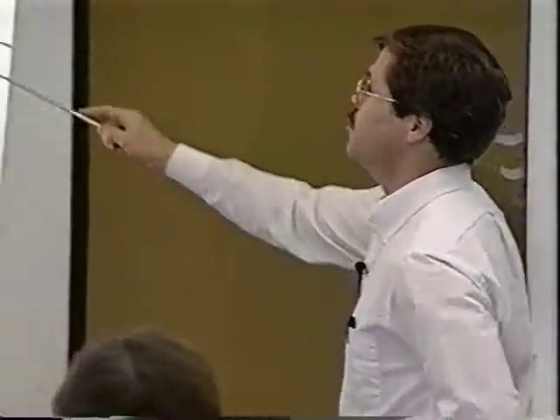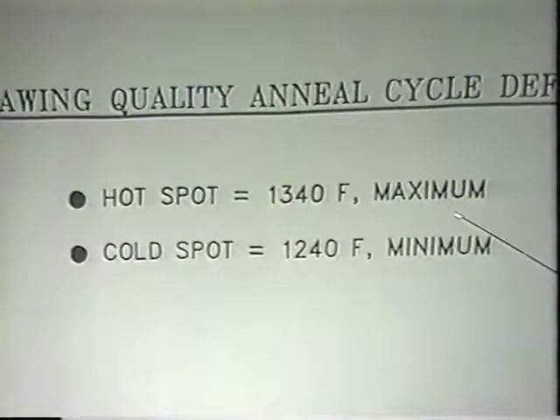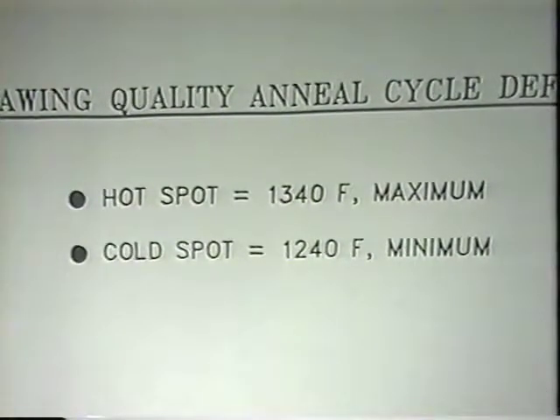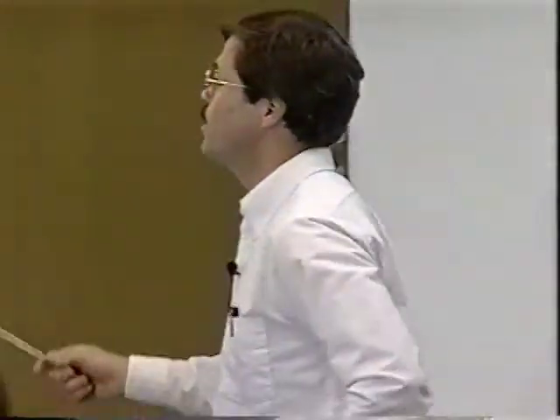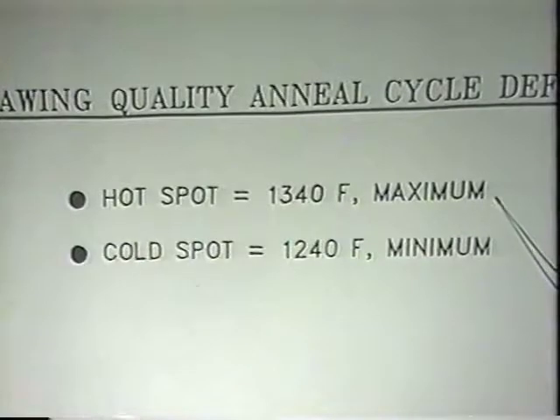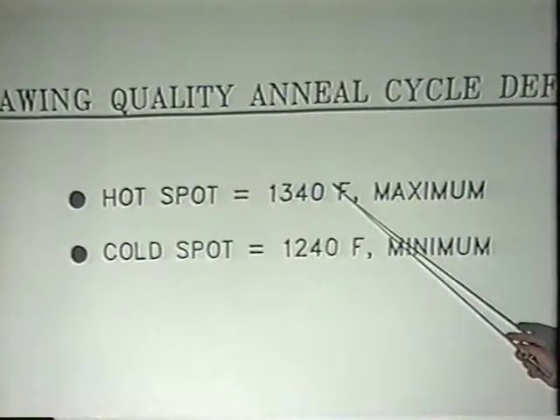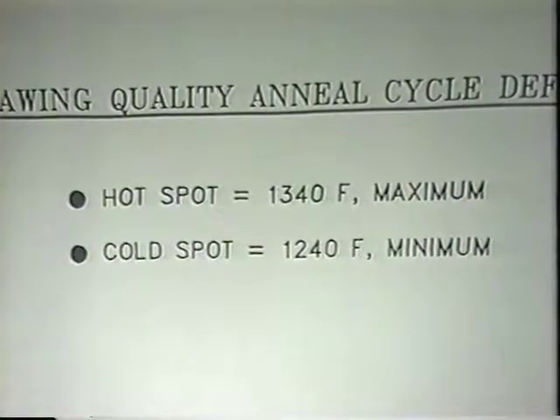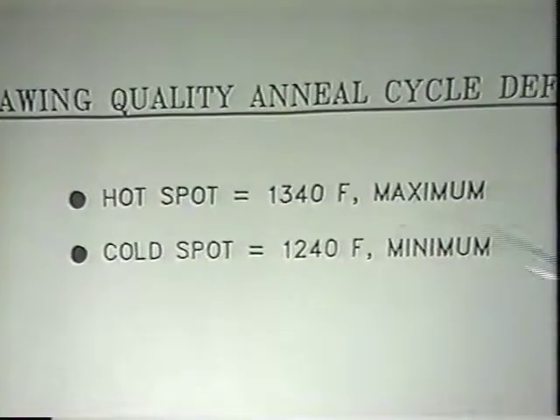We can make this window smaller by turning the temperature of the fire down, just like the chicken. If your coals are hot, you're going to burn the outer surface and you're still going to have raw meat. Same thing here. We try to do the process too fast with a furnace temperature which is too hot, we're going to exceed that temperature and never meet that temperature. So the faster your anneal process goes, the larger this window's got to be. Hence, if you want to reduce the gradient of the batch anneal and create a smaller window, you're going to drive to a longer anneal cycle.